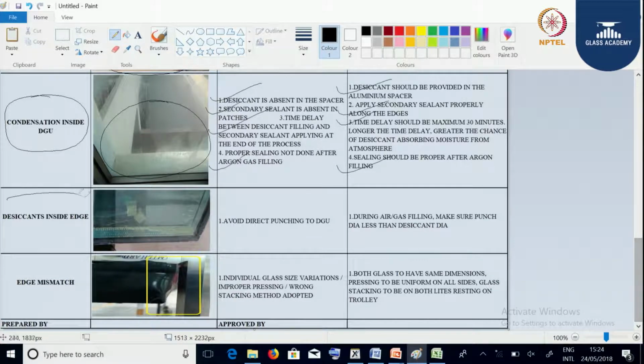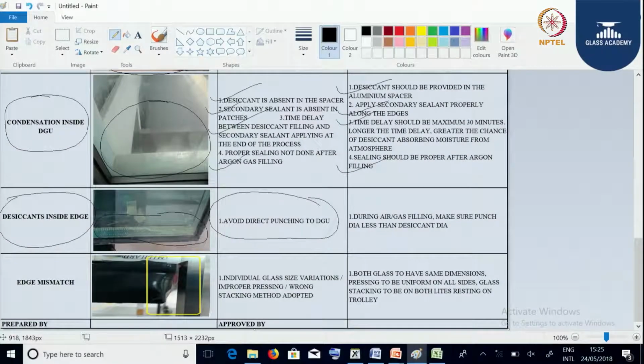The next defect is desiccants inside the DGU. You can see the desiccants have fallen inside the unit. This happens because of direct drilling or punching into the spacer, which should be avoided. Generally, whenever we see a glass with desiccant fallen inside, the major cause is that the DGU got drilled, so we need to avoid direct drilling of the spacer. We can overcome this issue during air or gas filling by making sure that the punch diameter is less than the desiccant diameter.